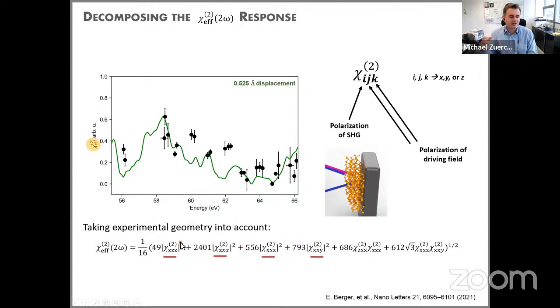And you can analytically calculate this by rotating, say, the crystal plane and rotating the tensor elements. So applying some tensor math, you can analytically arrive at this result. And this is now for our specific measurement that we did. This shows you multiple things. First of all, this is quite complex. So if you want to measure a certain response of the system in a certain crystal direction, you need to think very carefully about how to orient your crystal with respect to your electric fields. That's one thing you have to do.